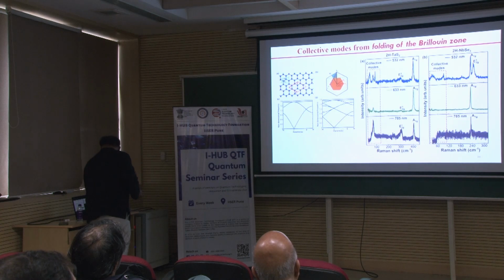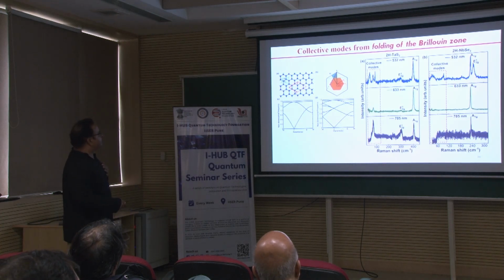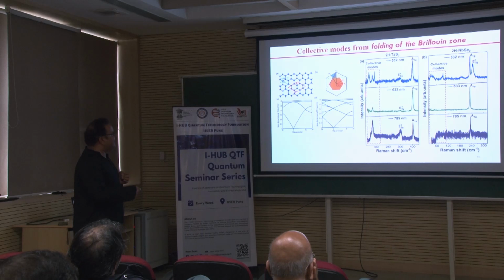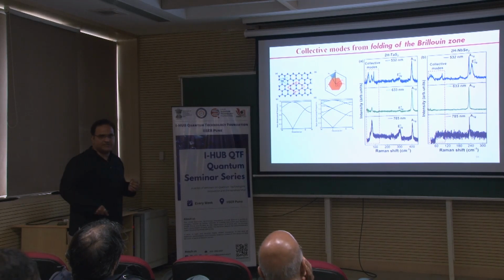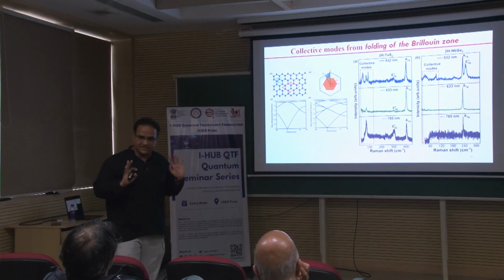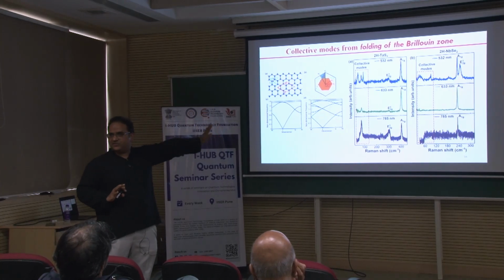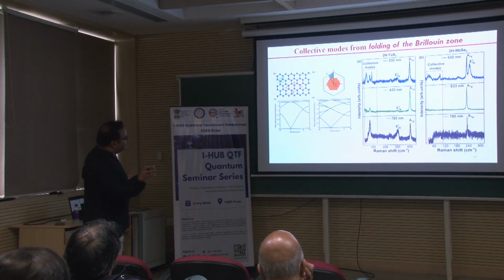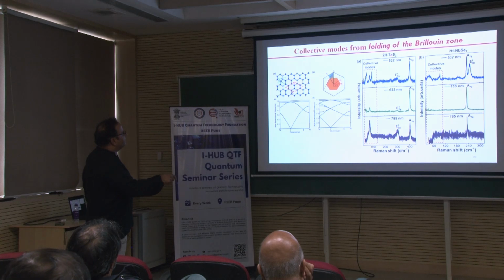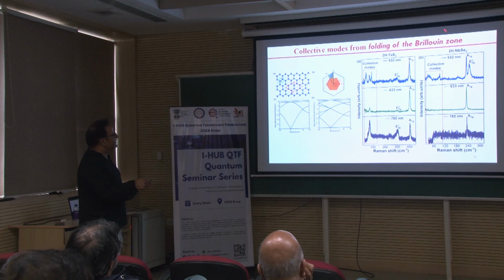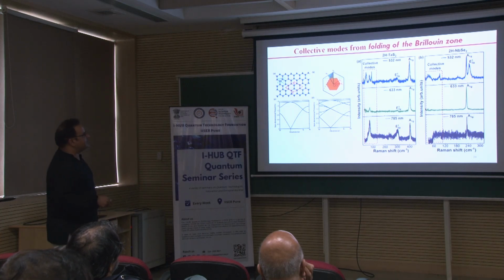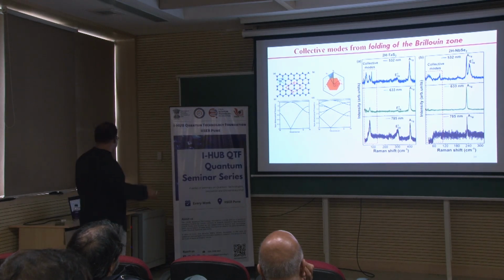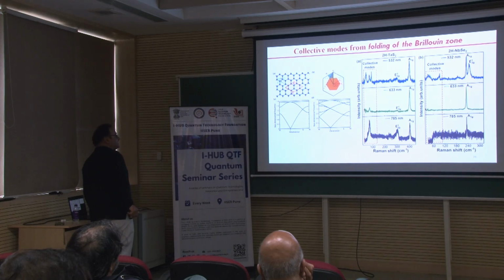effect of dimensionality. As I mentioned, there are charge density wave supermodes which are coming because of the folding of the Brillouin zone, and these are the modes we call collective modes, well reported in literature, which are seen in the Raman spectra. With 532 we have seen 3, because some of the lasers will not excite some of the modes. So, you have these modes, we call them the amplitude mode or the phase mode, and these are the super modes representing the charge density wave.